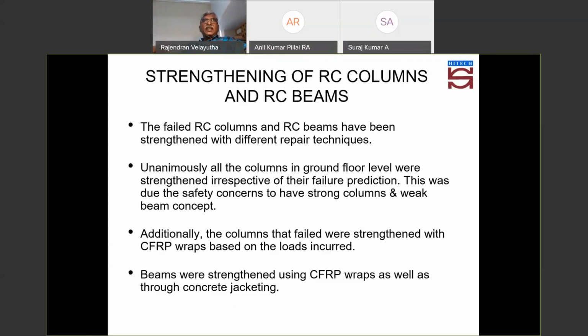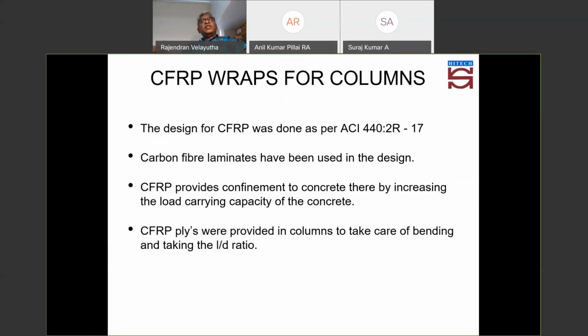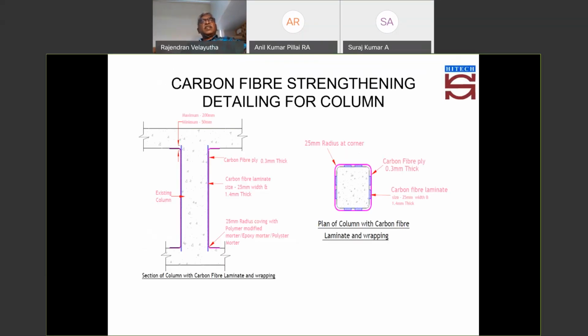When it comes to microconcrete jacketing, how do we go about it? If the concrete member itself is insufficient and there is definitely no point in going for a CFRP wrapping, then we need to go with increasing the thickness or depth of the member, either a column or a beam. Otherwise, you can very well go with the CFRP strip and then CFRP wrapping.